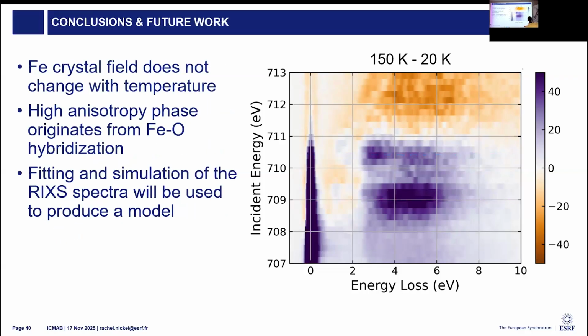right now. So our main conclusions from these experiments is that the iron crystal field doesn't change with temperature. The high anisotropy phase with the high coercivity originates from a change in the iron-oxygen hybridization, and the fitting and simulation of RIXS spectra will have to be used to produce a better model and better understand this system.